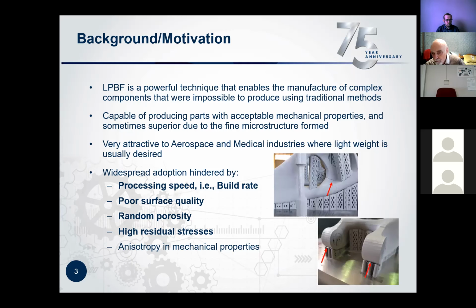Here, I'm just showing some pictures of a component that we attempted to build late last year. We were not successful in it. We had to stop halfway through the build because of delamination and cracking. The first delamination we didn't detect. If you look at the bottom picture between the part and the supports, we could only detect that later when we removed the part. And then there's cracking that took place just along the rib of the part.